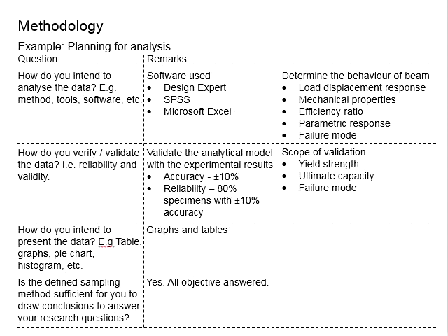Personally, based on my personal experience, for most engineering applications, this 80% of the specimen with the accuracy of plus minus 10% is considered good enough, having a certain level of requirement which is achievable. You know that the so-called plus minus 10% is equivalent to 20% variations, if you are talking about the minimum value and the maximum value within the range. And 80% here will be quite okay for you, as it represents a significant majority.